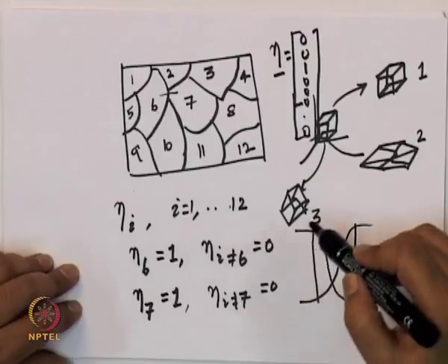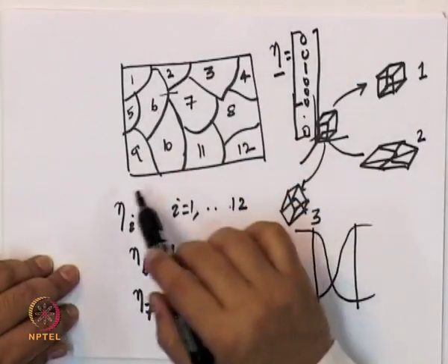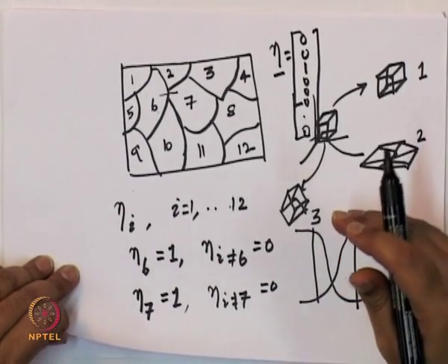Now, we have to write a free energy that describes such a polycrystalline or grain microstructure. We know that at the end, out of all these 12, any one of the grains can actually eat up all the others and become a single orientation. All the 12 have the same energy in the single crystalline state, because with respect to some external frame of reference we are describing them as eta_1, eta_2, eta_3, etcetera. It can so happen that eta_3 will survive, or eta_8, or eta_12, or eta_11. Whichever crystal survives, if you go to a single crystalline state, all of them should have the same energy.